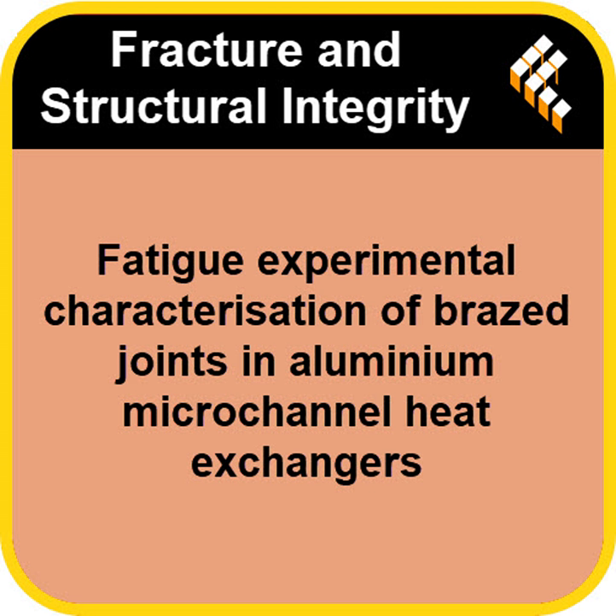Yeah. But there was something else, wasn't there? Something more intriguing found right near where the crack started. Yes. This was perhaps the most critical observation from the fractography. Right there in the crack initiation zone, near the surface at the fillet toe, they consistently found small particles or inclusions embedded in the metal. They didn't look like the aluminum itself. Foreign bodies, essentially. Exactly. So naturally, they analyzed their chemical composition using energy dispersive X-ray spectroscopy, or EDS.